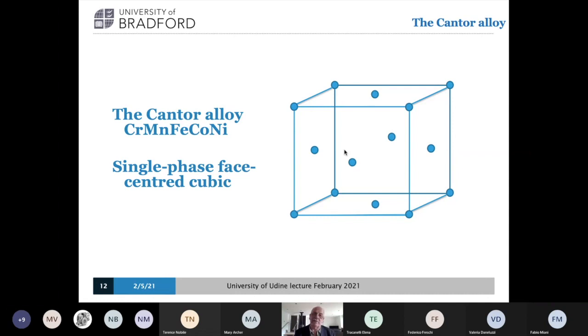And it turns out that this material has incredible properties. Now, it's not just one Cantor alloy. It's literally hundreds of thousands of Cantor alloys, because you can add other components into it and the alloy range is enormous that you can have, which has this single face-centered cubic structure. In the middle of that 5-component phase space, the tetrahedron, or the next stage up, because it's got to be 5 components, in the middle there's an enormous patch of region which has a face-centered cubic structure like this, which nobody predicted. And people are now beginning to look at the properties, and they've discovered that they've got great properties.